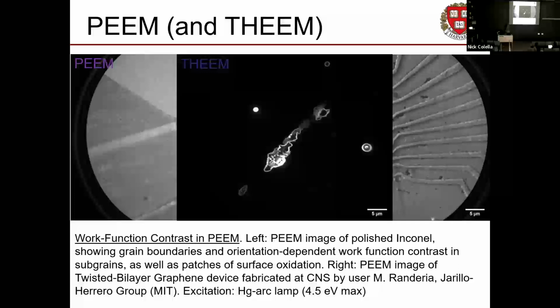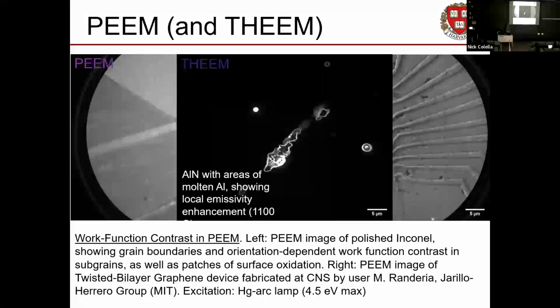So if you put a piece of, in this case, aluminum nitride, and you get it up to 1100 C, yeah, it starts making electrons, sure. Why not? You take pictures of those too. I don't know of any actual practical use for this phenomenon, but it exists. It's not listed on the instrument when you buy it as an imaging mode, so I was kind of shocked because that actually works. But cool.